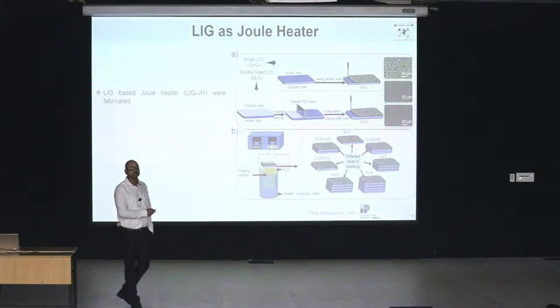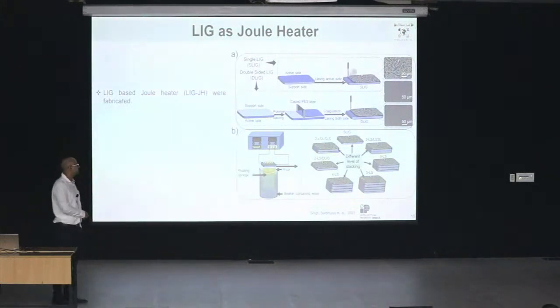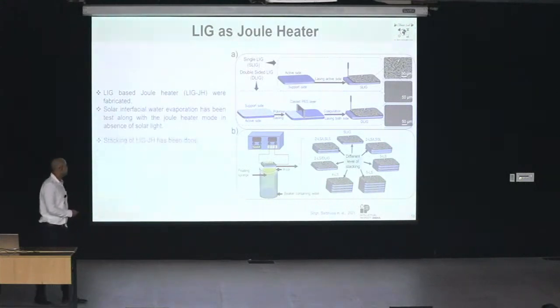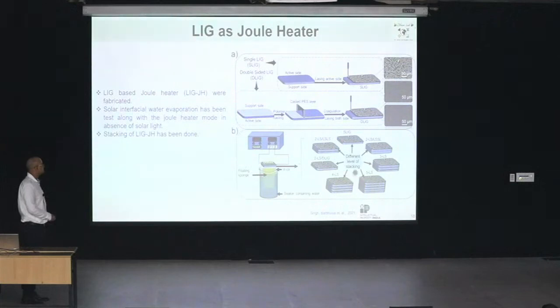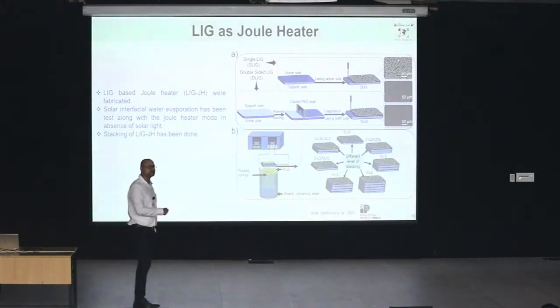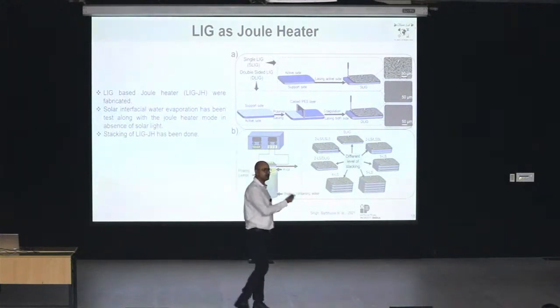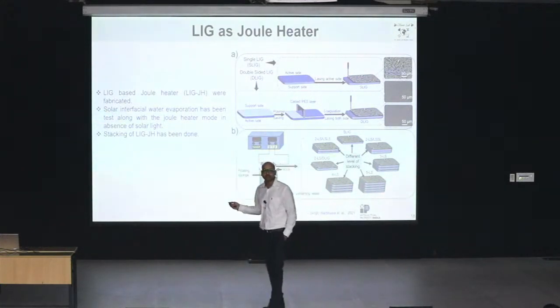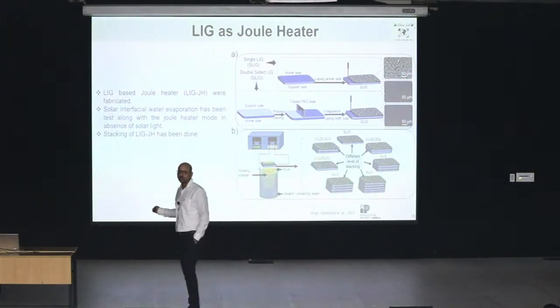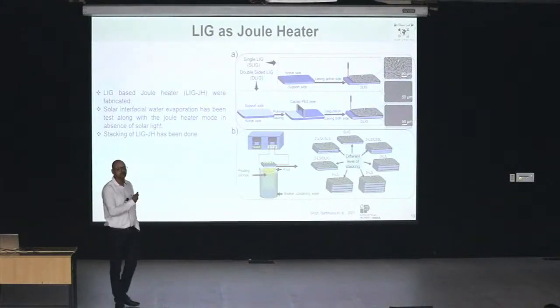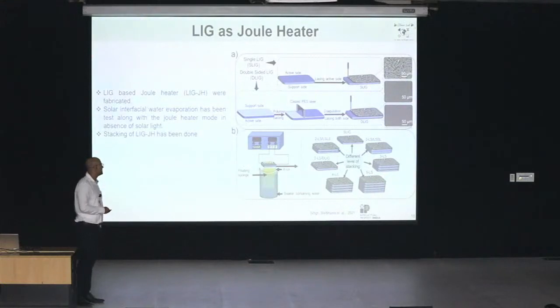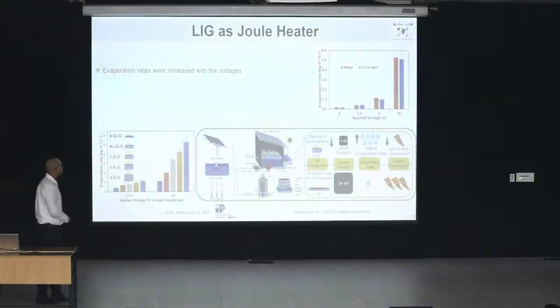To demonstrate this phenomenon, we also made different kinds of Joule heaters in a single step. We have tried to stack them to conserve energy, and recently we have demonstrated that by stacking these laser induced graphene filters, we can do very effective desalination, both in the presence of sunlight, and when sunlight is not available, we can use the stored energy and run this system in a Joule heating mode, and we can generate water. So this system can work in any kind of weather if we integrate it with solar power. When sunlight is available, it will be able to generate the water. When sunlight is not available, or you need an accelerated rate of water, we can go in a Joule heating mode.